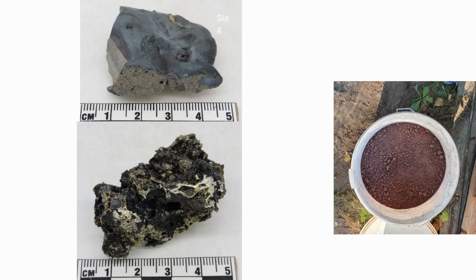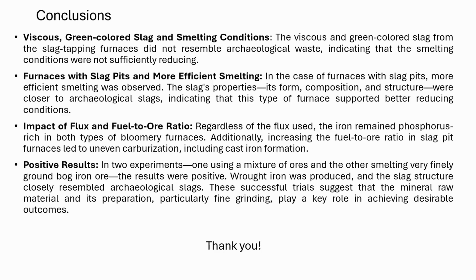So, after conducting 10 smelting experiments with ore from the same deposit, identifying the variables that most effectively reproduce archaeological material remains challenging. The viscous and green colored slag from the slag tapping furnaces didn't resemble archaeological waste, indicating that the smelting conditions were not sufficiently reducing. In the case of furnaces with slag pits, more efficient smelting was observed. The slag's properties, its form, composition, and structure were closer to archaeological slags, indicating that this type of furnace supported better reducing conditions.